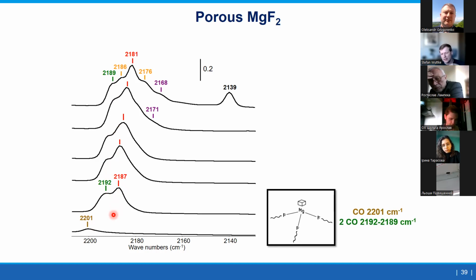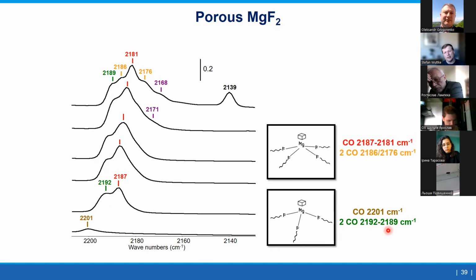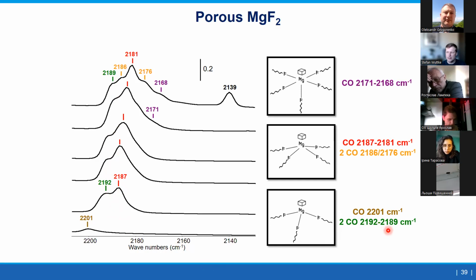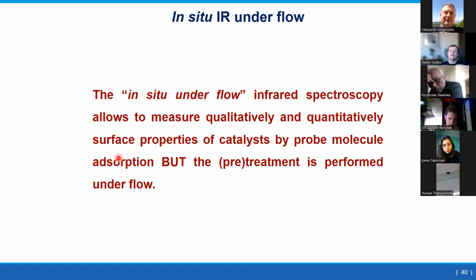And the strongest Lewis acid was here undercoordinated magnesium fluoride, which just had 3 fluorides on it. And you have 1 CO, but also 2 CO molecules can go on this and then vibrate on this. So these vibrations. Then we had 4-fold undercoordinated magnesium, and then we had 5-fold undercoordinated magnesium. So like this, you can study the different Lewis acidity species on the material. And if you could deconvolute here the surface under these peaks, so you have the peak area, and you would have the extinction coefficient, you could even calculate the amount. But you see that they are too close together. You can make assumptions, but they're not very accurate. But the next step is, so we have now in situ, so we can under inert condition study the sample qualitatively and quantitatively.